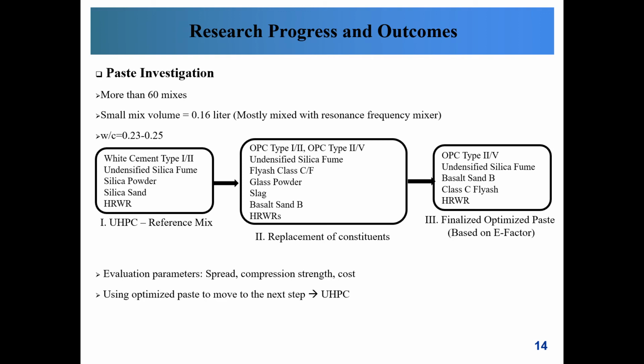So first, we started with our house UHPC mix as a reference mix, using white cement, white silica fume, silica powder, silica sand, and high-range water reducer. Then we replaced several material constituents one at a time, for example, changing the type of cement, type of supplemental material, which included fly ash, glass powder, and slag, and switched to basalt aggregates, locally available here in Connecticut.